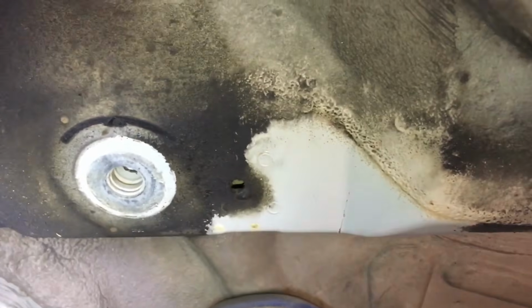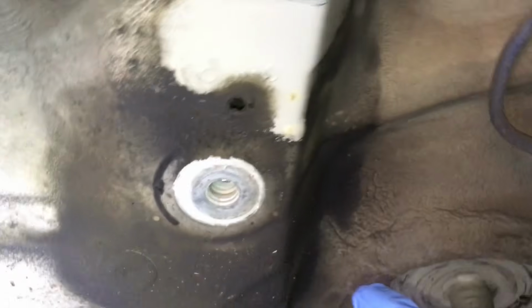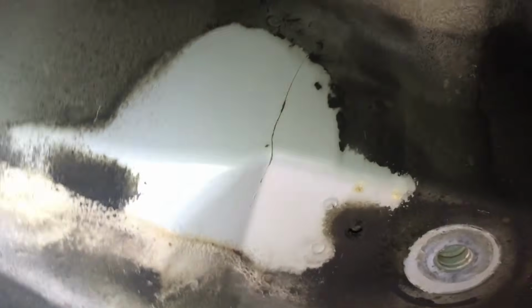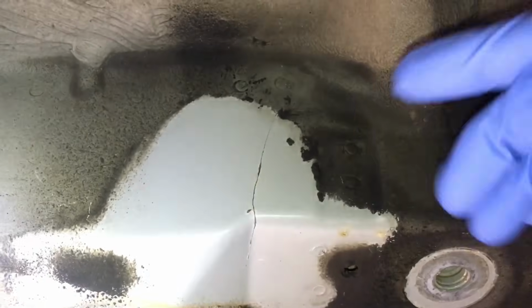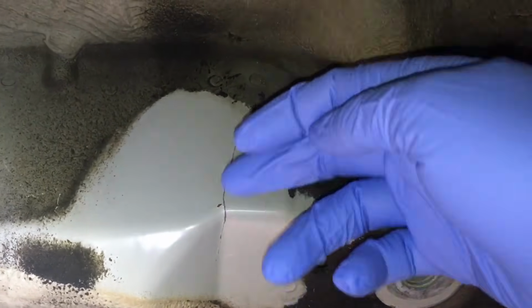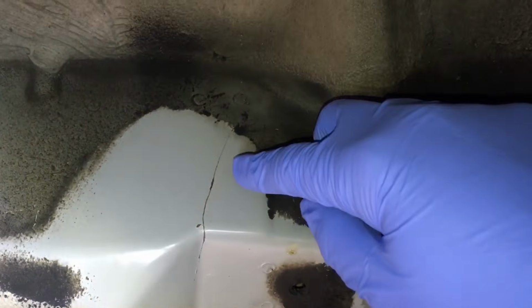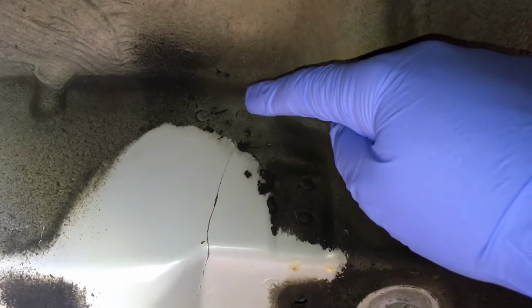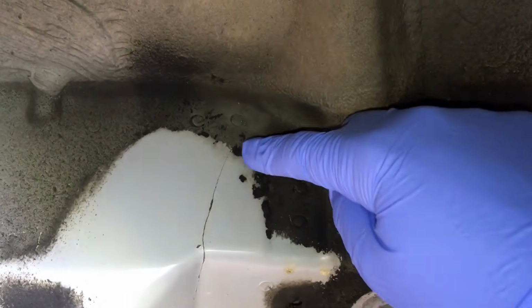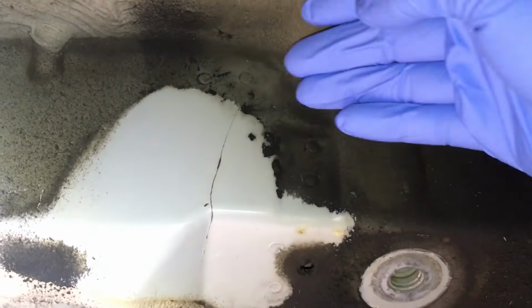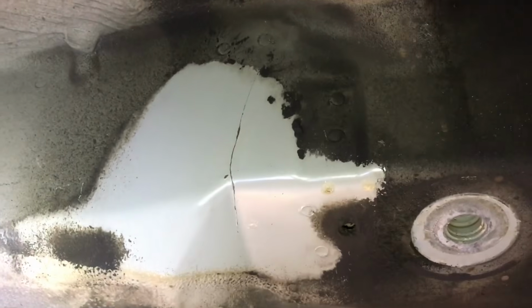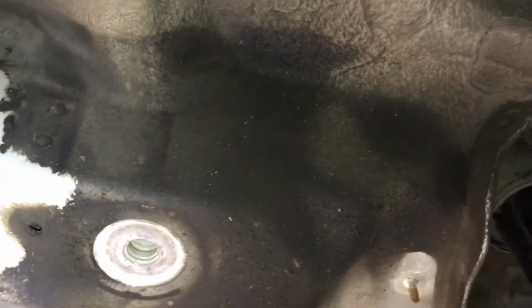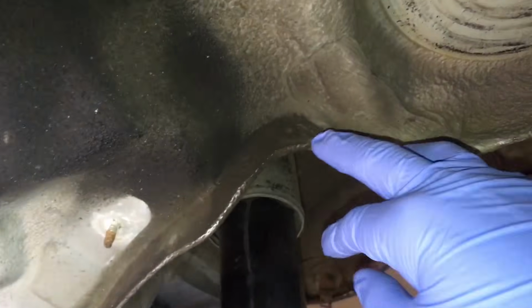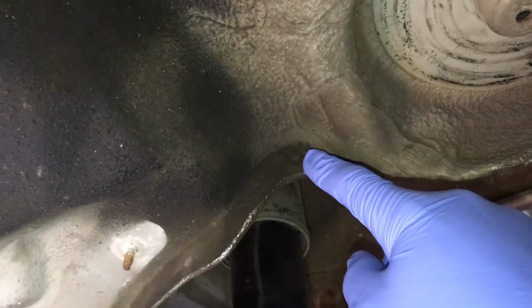So this is the one that we talked about in the video earlier that we could see, which is going along the horizontal plane. And then the vertical plane, where it goes around the corner, is a decent length actually, quite a surprise. It's the largest one we've done on a 2006. Haven't yet cleaned enough off to see whether it's reached that spot weld up there or whether it's going to go past it or even not make it up to it. But definitely hairline crack there, quite large in length, and that needs to be addressed. And then that one spot weld that looks likely to be broken up there.